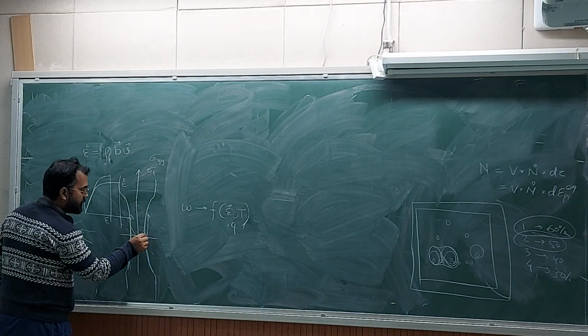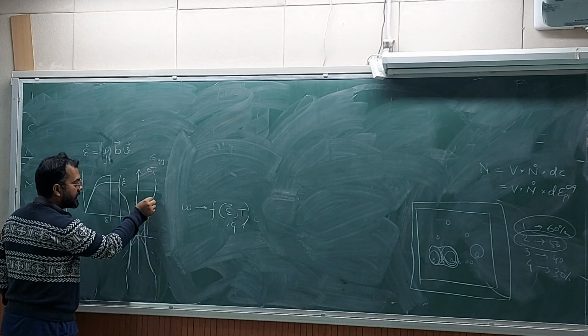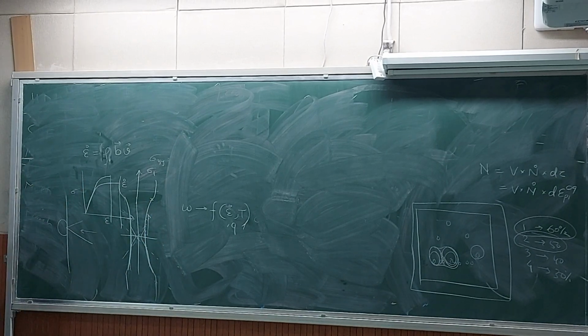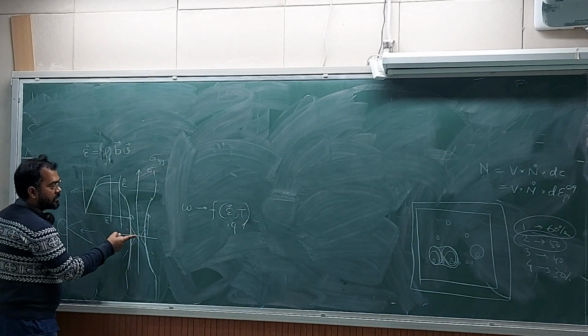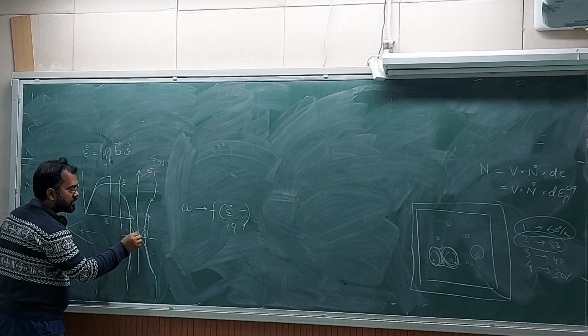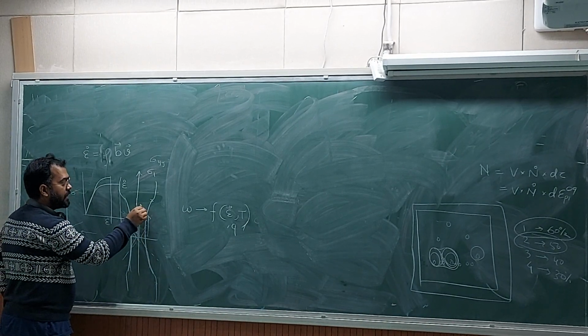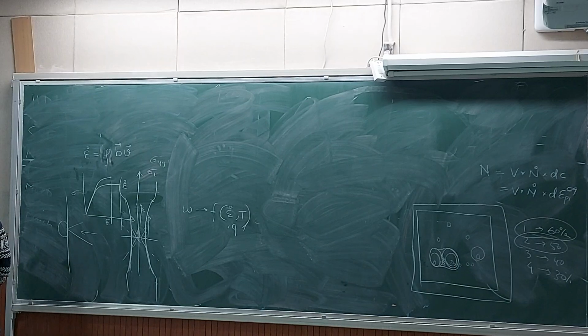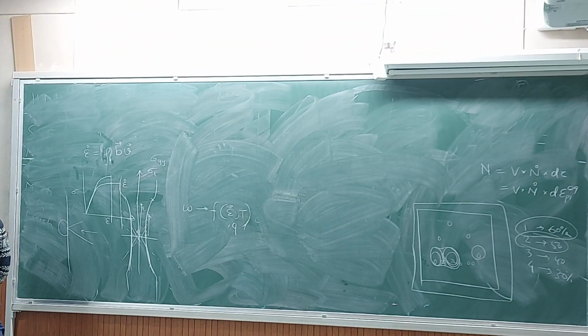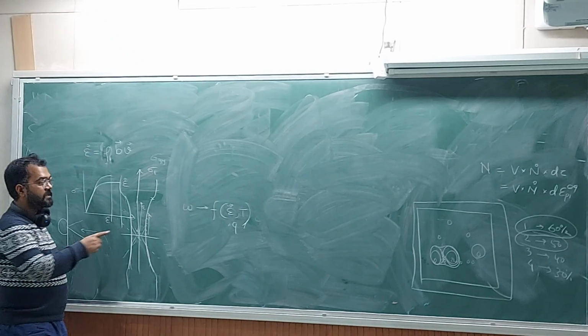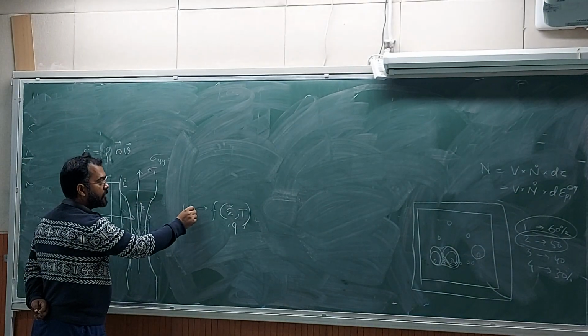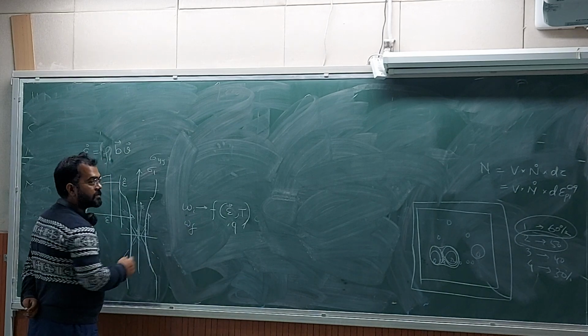I have more strain here, less there, less there, less there, and elastic there. So I can find out the void volume fraction with a change in strain. So as a function of strain I can find out. Okay. So then I know my damage kinetics, how it goes from Wi to Wf as a function of strain.